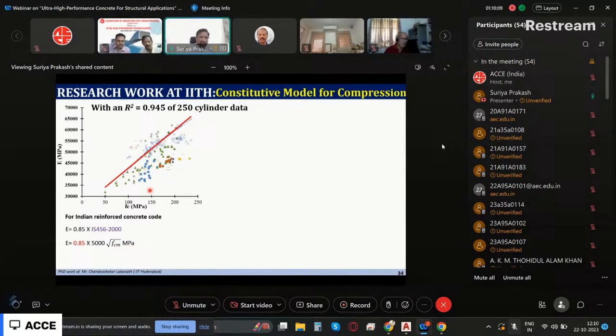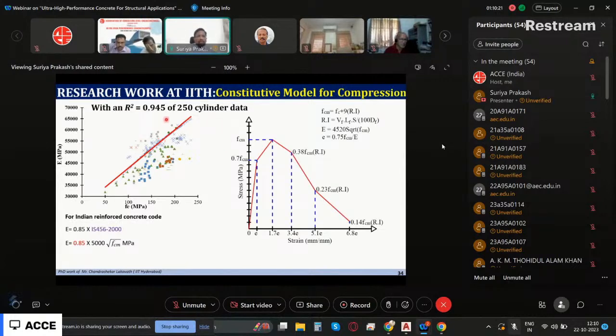Instead of cube strength, here we are talking about cylinder strength. But in UHPC, again, the difference between cylinder strength and compressive strength of cube is not much. Cylinder strength is only about 0.95 times the cube strength. Then using all this data, finally I need to get some stress strain curve model to be used in design. So we came up with this kind of a multilinear stress strain curve that can be used for your design.